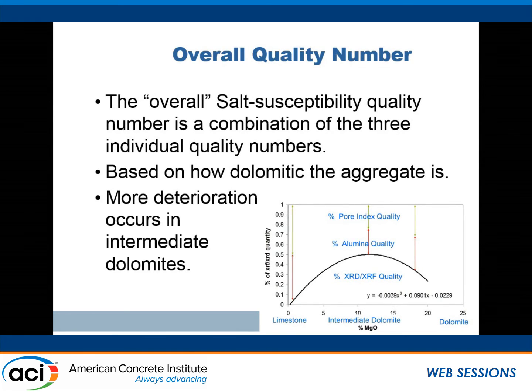Then there is the issue, okay, we've now got these three quality numbers. We've got the XRF, we've got the pore index, and we've got the XRD-based numbers. Which one's most important? And the answer is it all depends. If you have something on the limestone end of it, the XRD side of it is not that critical. And so then it's a pretty equal balance between the pore index and the clay content as being contributors to the risk of deterioration. If you're at the high end of the dolomite scale, the XRD is critical but not so much, and again, balancing out the other two parameters. If you're at that intermediate dolomite, 10% magnesium, then the XRD is probably the most critical parameter within the system. So it's a graduated scale depending on the system that you're dealing with.